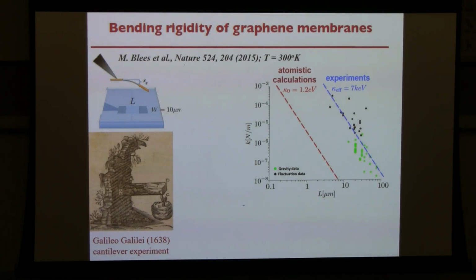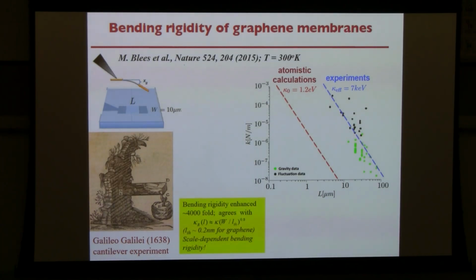Either way, you get a measure of this bending rigidity. You get a measure of this thing for different lengths. They always had the same width. And when you track these different spring constants for this vertical displacement, they in fact all fall on a nice line that goes like 1 over L cubed. That's expected. But the amplitude is about 4,000 times bigger than you would have expected at 0 temperature. So in fact, there's a huge amplification.